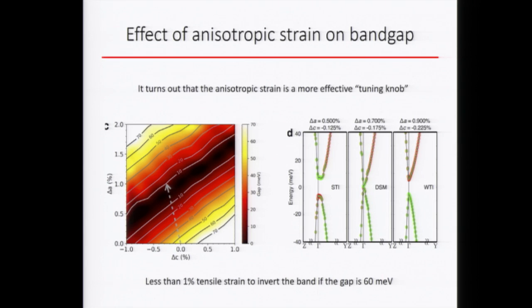You can see there's a valley here corresponding to 0 gap, also corresponding to the topological phase boundary between strong and weak. The most efficient way to go across the phase boundary is extending the A lattice constant and contracting the C lattice constant. If you go for isotropic expansion or compression, you're basically going parallel to the valley, so you need a very large amount of strain in that direction to go across the boundary. The gray arrow corresponds to the actual Poisson ratio we apply. It's not the most efficient, but it's efficient enough that we actually see some signature of the topological phase transition.